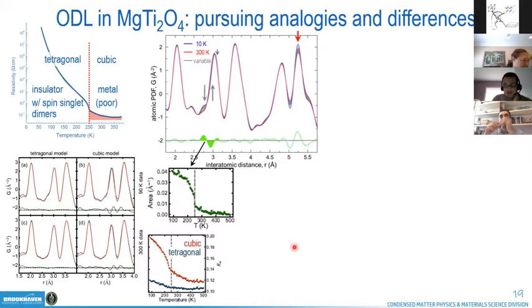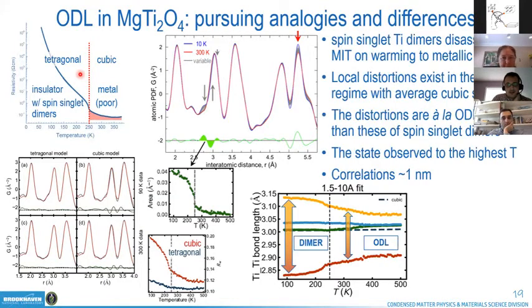But the ultimate idea of what is going on in this system still comes from modeling. We have fitted this tetragonal model as a function of temperature throughout the metal insulator transition. What we observe is that at low temperature there is a dramatic distortion of titanium nearest neighbors, a signature of the spin singlet dimer, that gets removed at the transition, but it evolves into a much smaller distortion.